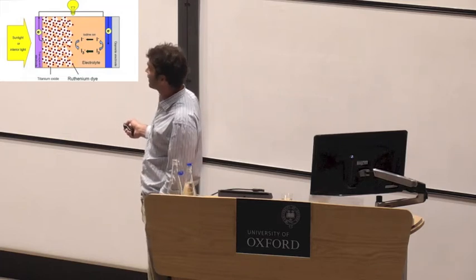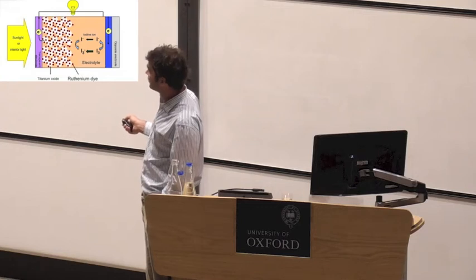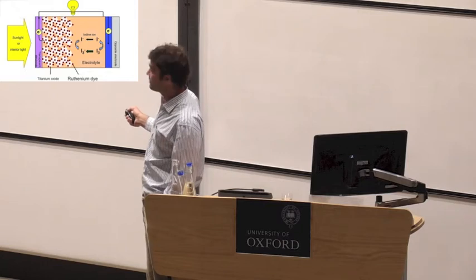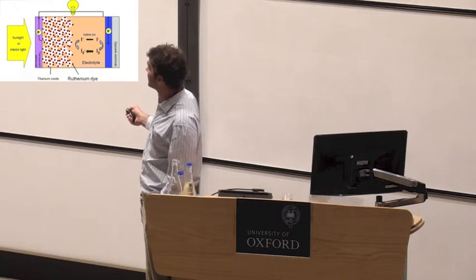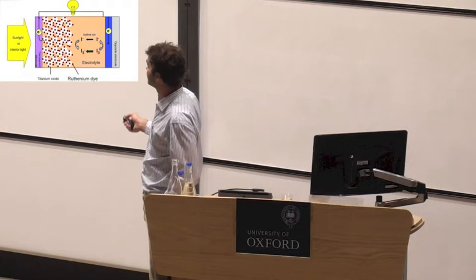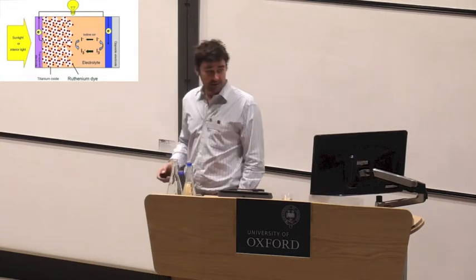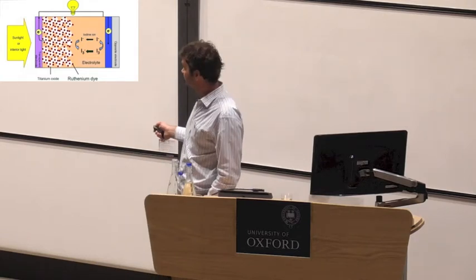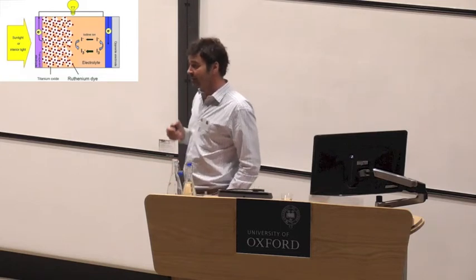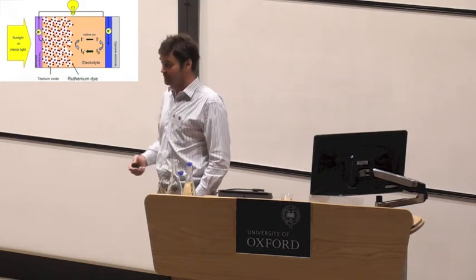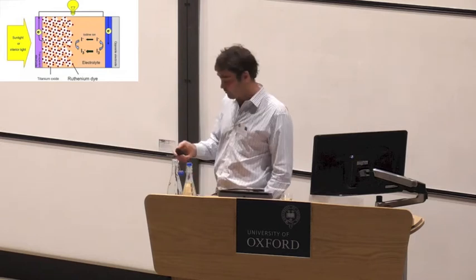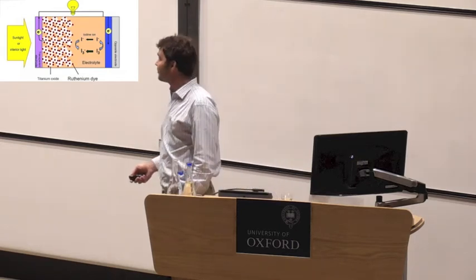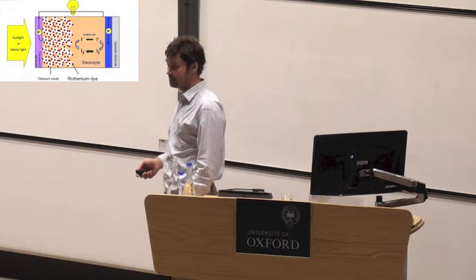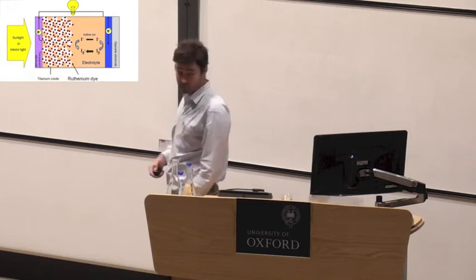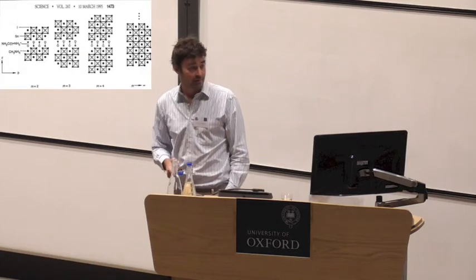So we have to have this bulk heterojunction, which is either made of all organic materials, or it's a hybrid approach where we're using metal oxide nanoparticles here coated in a dye. And this is called a dye-sensitized solar cell. These technologies have pushed up the power conversion efficiency to around 12%, but they look like it's going to be a big challenge to get them much further. And silicon's still coming down in price, so we sort of need something else, another sort of material that's cheap and can make solar cells more similar to silicon or crystalline materials.